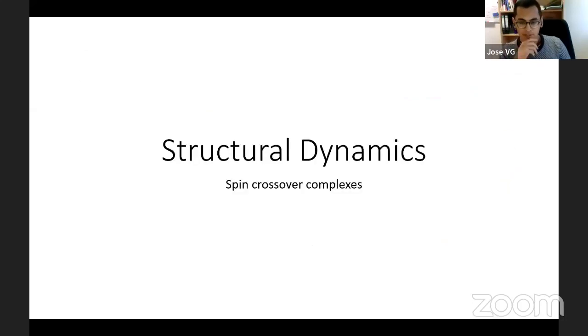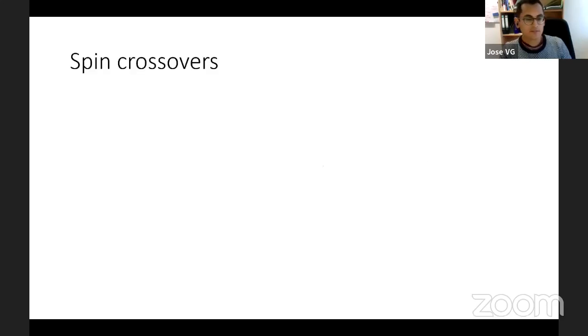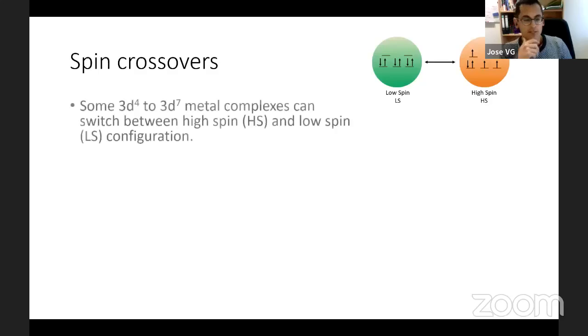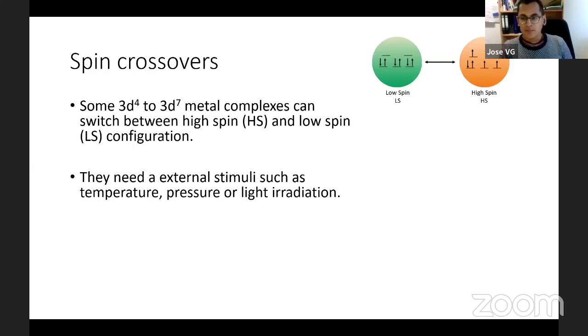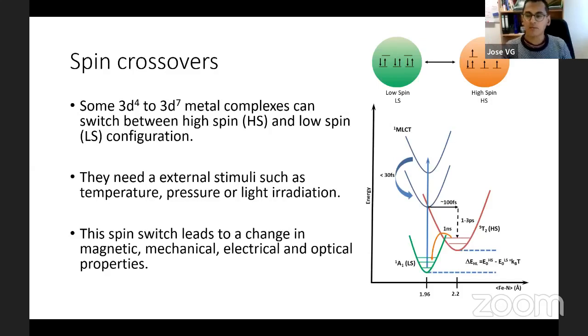Okay, so for example, one of the typical things we use time resolved photocrystallography for is spin crossover complexes. Spin crossover complexes, some 3d4 to 3d7 metal complexes can switch between high spin and low spin state configuration. This change can be made by temperature, pressure, or light. The importance of these complexes is that by changing this electronic configuration, there are also changes in properties. For example, there is a change in the magnetic properties, there is a change in the mechanical or electrical or optical properties. In our case, because of the photocrystallography technique, we are more interested in the